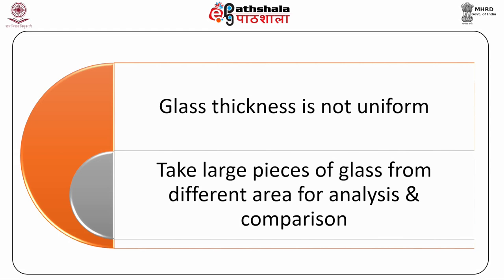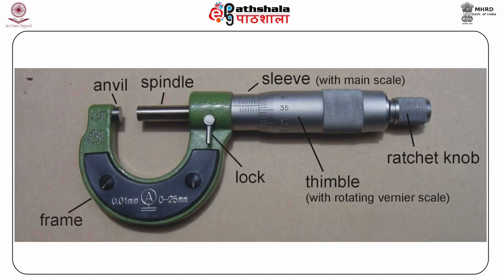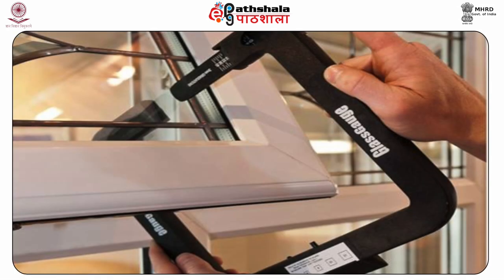First comes edge thickness. A micrometer is used to measure accurately the edge thickness of a glass fragment. Readings should be taken all around the broken edges to find out at which point the crime exhibit matches with any portion of the broken glass. This will further help during the matching of surface patterns and other identifying characteristics along the broken edges.